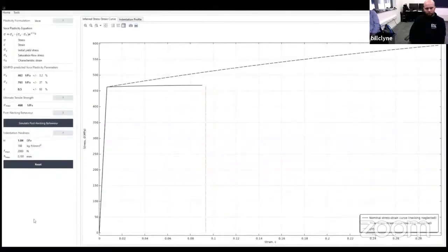Now that the calculation is completed, we can see here we are using the Voce plasticity equation, and underneath are the parameters that SEMPID has calculated in that equation for our stress strain data. On the plot, the dotted line shows this plotted as a true stress, true strain relationship, and the solid line shows that true stress, true strain relationship converted to a tensile nominal stress strain. This also allows the calculation of the UTS, or ultimate tensile strength, which here occurs at approximately 10%.